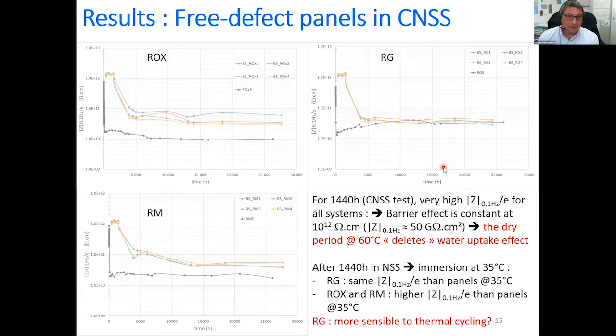Now, these are the results of the free defect panels in the cyclic neutral salt spray. So during the first 60 days in salt spray, as you can see, the barrier effect doesn't vary. It is quite constant. There is no evolution of the barrier effect, no evolution of the reduced impedance modulus. This is true for the three different systems. In fact, we think that the dry period at 60 degrees deletes the water uptake effect, and there is no decrease of the barrier effect.